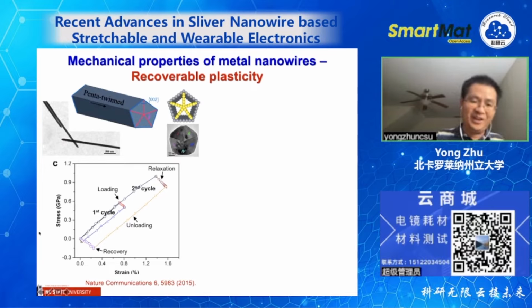What happens here is quite interesting. Here it shows the strain behavior. You have an elastic deformation, and then you have some plasticity and so on. But then when you unload, very interesting is the recovery. You see, the plastic deformation can be recovered. Something we call recoverable plasticity.